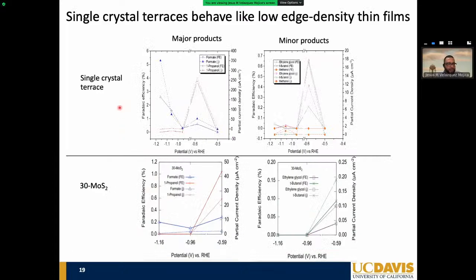That allows us to protect the entire crystal under electrochemical conditions and only expose the area that is within this window, okay? So when we did these experiments, we basically compared a single crystal, where we did some microscopy to verify that we indeed have a lot of terraces exposed, and our sputtered, thermally converted MoS2 thin film on the degenerately doped silicon. We're still seeing propanol. However, in the single crystals, we do see a bump of Faradaic efficiency from 1% of converting CO2 to propanol to about 4 to 5%.